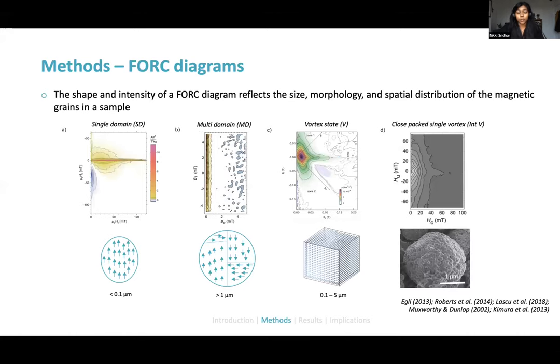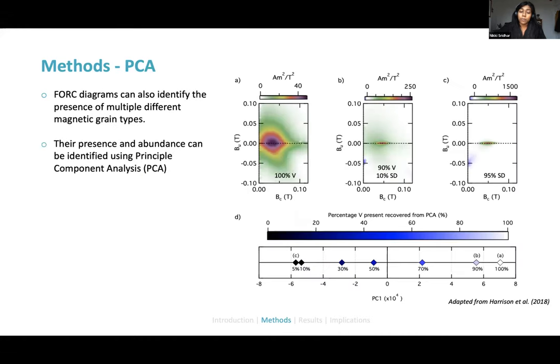To do this, we measured a range of FORC diagrams, which are really useful because a FORC diagram is distinct for different magnetic domain states seen in different magnetic grains. Importantly, because natural samples normally aren't monomineralic and contain multiple grain types, FORC diagrams can show contributions from different magnetic domain grain types. We can use principal component analysis to unmix these different signals and identify what different grains are present in a sample and how much of each.